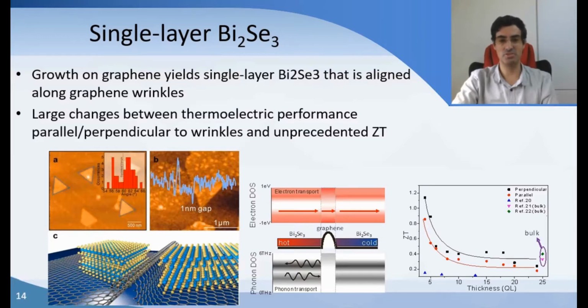And so that means that we can use that for seeing the anisotropic behavior of the thermoelectric performance. We see that perpendicular to the wrinkles, we get a higher ZT because the phonons are more efficiently scattered than electrons, and parallel, the ZT is lower by about 50%. Also, we see the appeal of using an inert substrate because we can actually grow down to a single monolayer or 5 quintuple layers of bismuth selenide using graphene. So this is one application that you couldn't do with silicon, for example: growing ultra-thin, high-performance thermoelectrics.